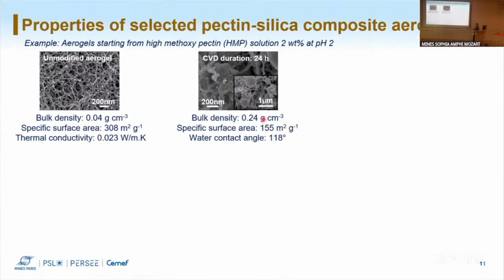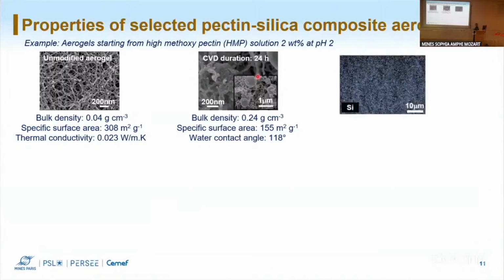When we see the structure with scanning electron microscopy, we see that inside our network, we had the formation of some silica nanoparticles, which appear to be non-dense, as we saw also from the surface area values. So we wanted to adjust our process to avoid the formation of these particles. We tested to see if the silicon was distributed in the network. From interior pieces of the material, we could see that silicon was very homogeneously distributed. So the reaction could reach all the parts of our material.